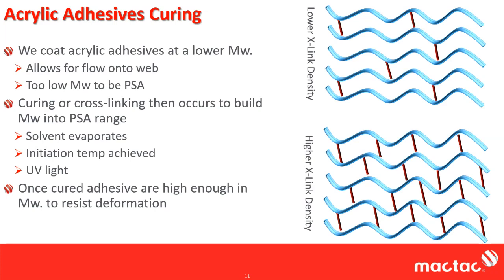One, you can have the solvent evaporate. This is your self-cross-linking types of acrylics; most of what's coated today for solvent acrylic adhesives are self-cross-linking. You have a catalyst in there, we call it a metal chelating agent, that kicks off the reaction, and it's surrounded by an inhibitor, which keeps it sterically hindered, which means basically there are these big molecules that don't allow that little molecule out to go find reactive sites. And as the solvent evaporates, that inhibitor evaporates, and that's how you get the self-cross-linking. So that's already built into it. There's no need to add any secondary cross-linker.